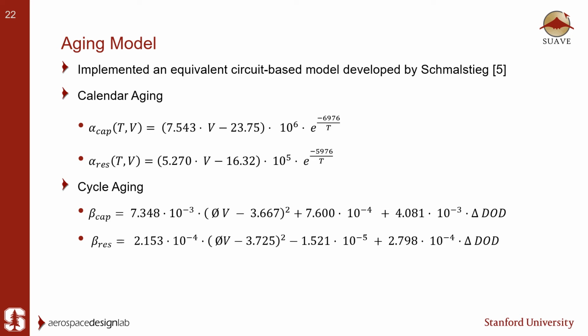Here we see this model is made up of two parts: calendar aging and cycle aging. The electric current profile, ambient temperature, and the depths of discharge are used to determine stress factors caused by volumetric changes in the intercalation and deintercalation of lithium ions, which I spoke about earlier, which is essentially the ions bonding and releasing from the anode and the cathode structure during discharge and charge. The repeated cycling of the battery induces capacity loss and internal resistance growth, and therefore can be seen using the equations seen here.